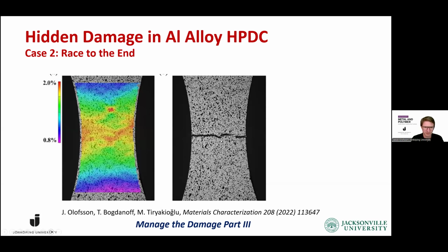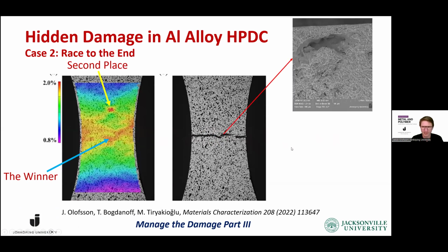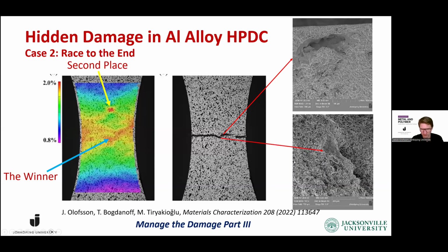We can see that as the fracture proceeds through this thinnest area, it follows these red indications that were seen also in the strain field at this low load. So this is really clearly the winner, and we had something in the top here that comes up in second place in the run on where to cause the fracture. Investigating this fracture surface closer in the SEM, we also see here that there's a very small pore, but also with an associated oxide, and where you see this kind of dimple that goes down in the fracture cross section, we see that there are 2 oxides competing, that has caused this branching of the crack during the fracture.